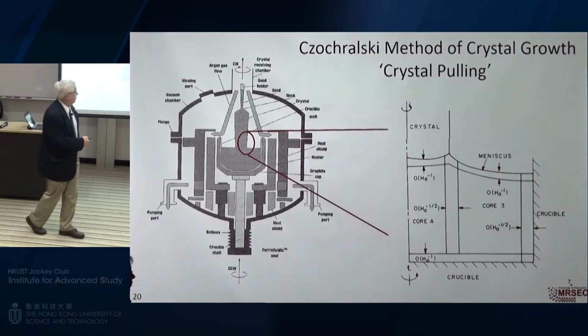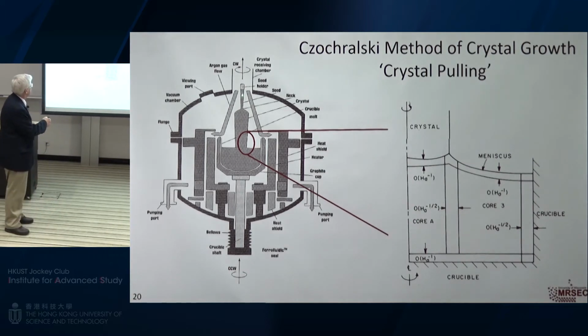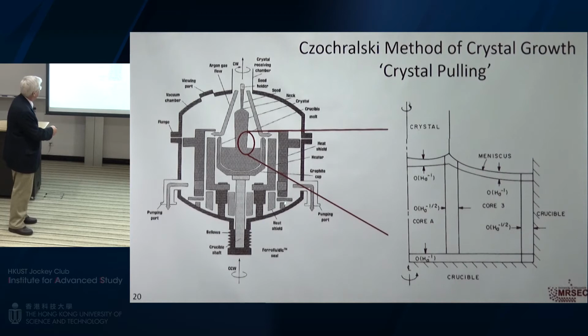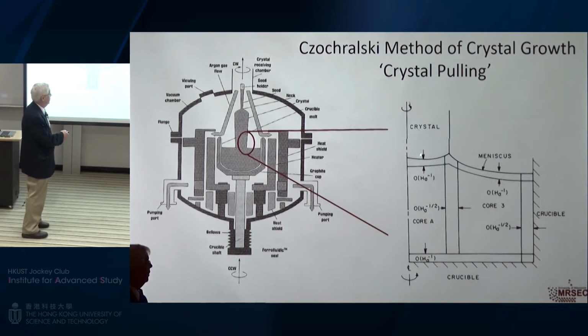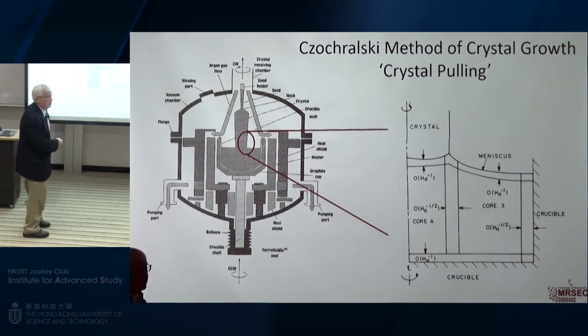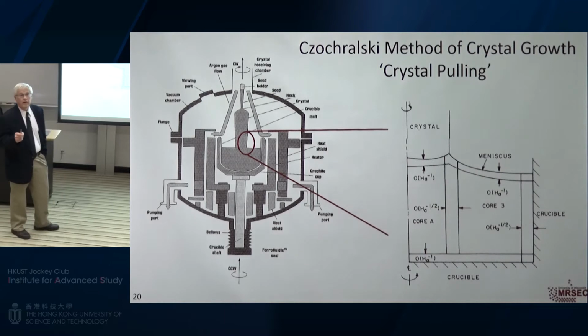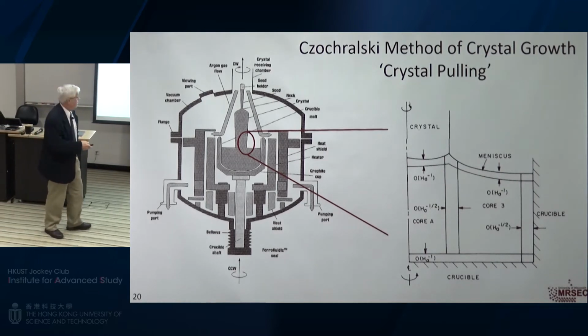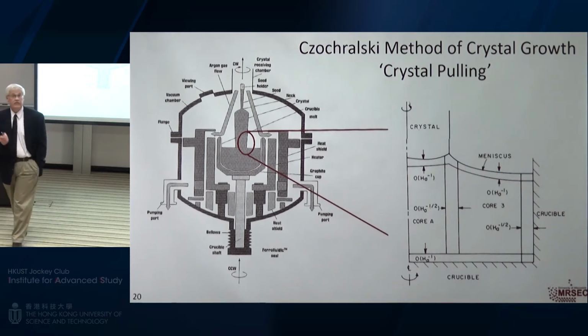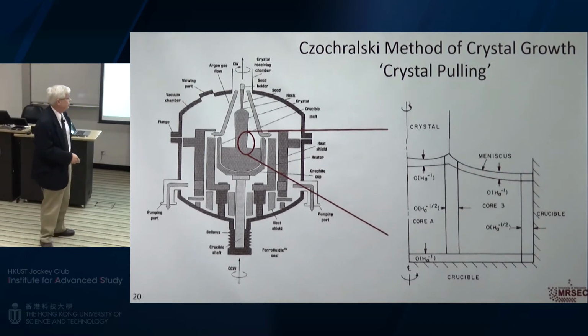But if I look at that crystal growth system, I basically dip a seed into liquid molten silicon, and I control the growth of the crystal by just controlling the heat removal at this interface. The rate of heat removal tells me how fast I can get the enthalpy of solidification, or the latent heat of fusion, out of the material. And so at that interface, it is at equilibrium. And I'm just pulling it up a little bit and cooling it off. So I have a little bit of what they call undercooling. And that undercooling is so small that this is basically at equilibrium. And I can calculate all the properties of the crystal based on equilibrium: its defect density, the number of vacancies it has, the amount of oxygen it has, and so forth.